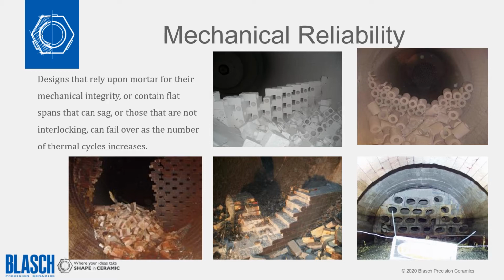The lower left-hand photo is a series of bricks mortared together in an open weave pattern. The top center are stacking blocks. Bottom center is a baffle wall. A variety of different construction techniques, none of which are particularly reliable. Part of the problem with this is related to the strength of the mortar. Mortar in and of itself is not a particularly strong bonding mechanism, and at high temperatures can only exhibit strengths of maybe 500-600 pounds per square inch shear strength, whereas the refractory material you're trying to adhere together will have 10 times that strength.